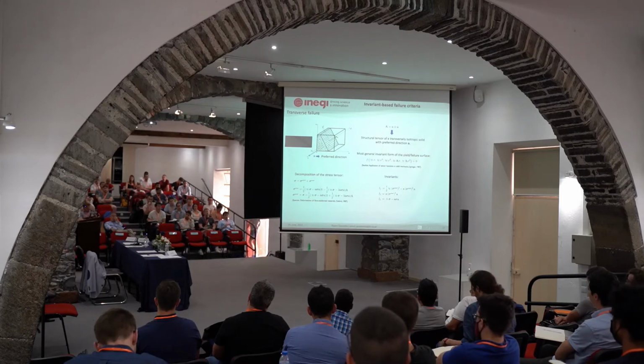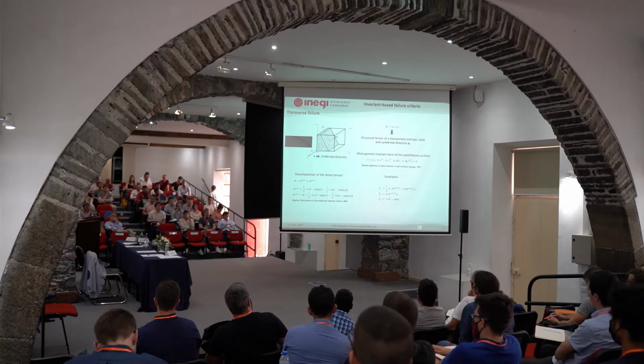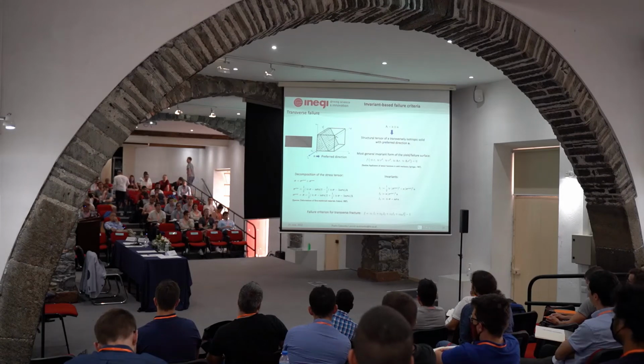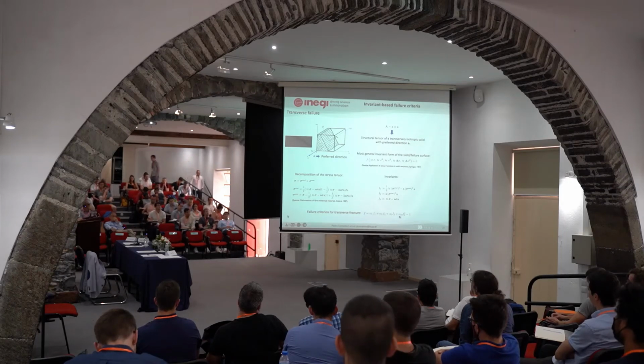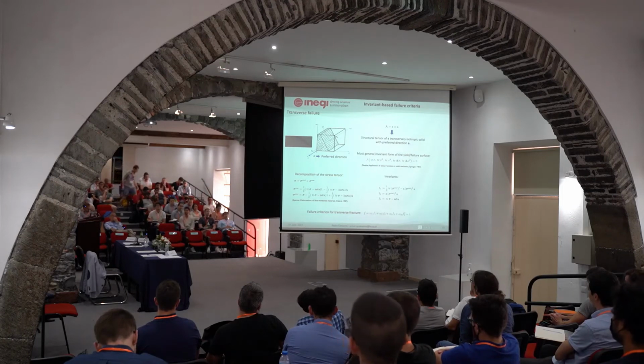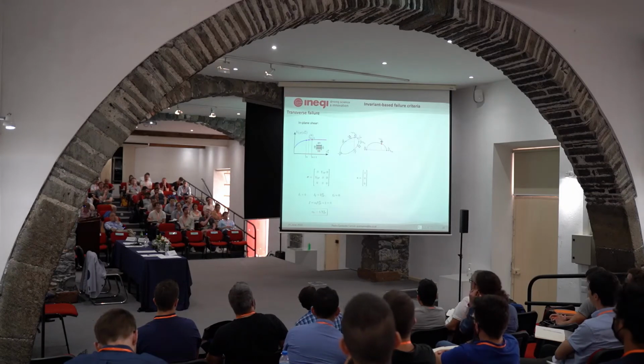Okay, so you get your stress from your finite element model or some analytical solution, and you just calculate the invariants, and then we get this failure criterion where the invariants here are driving failure, and the alpha parameters are material properties or functions of the material properties that resist failure. So I'll show you, it's very easy to identify the model. Like I said, it's a fully three-dimensional model, so there are no restrictions there. And I'll show you how we can identify the model.